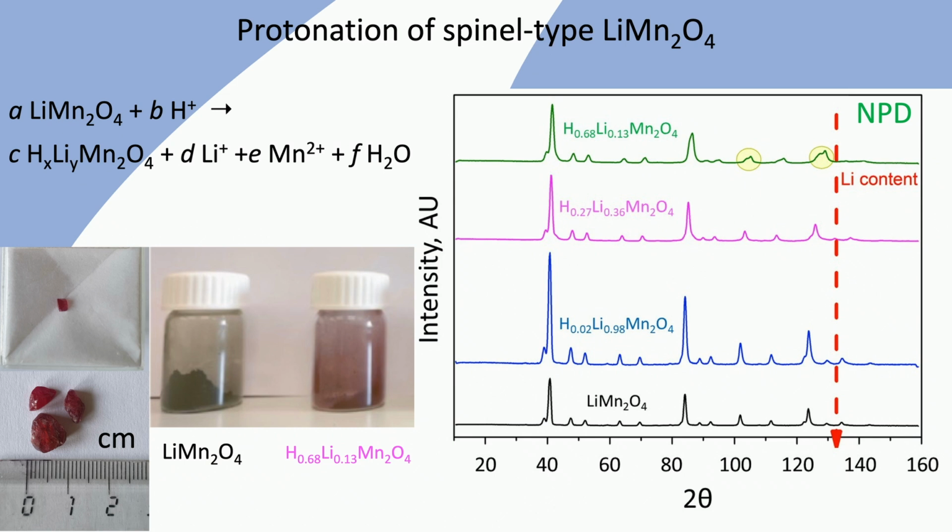In contrast, the protons prefer to go into the corners of the tetrahedron. These positions are known as the 96g sites. By the way, the numbers 8 and 96 before the a and g indicate the number of equivalent positions in the unit cell of the crystal. These new positions have implications on the various planes in the crystal and are nicely visible with neutron powder diffraction.